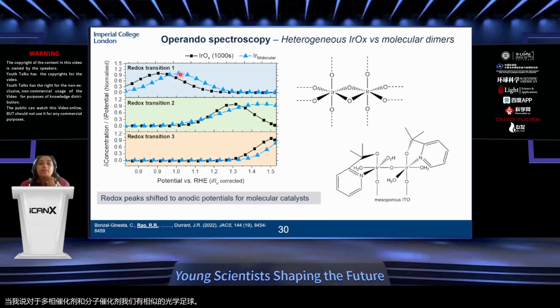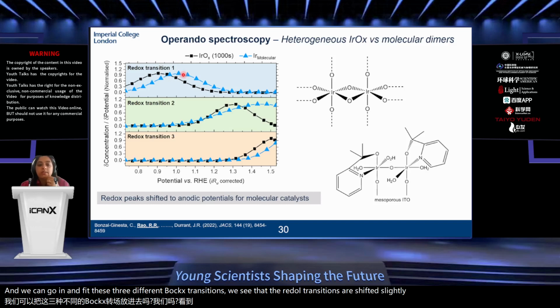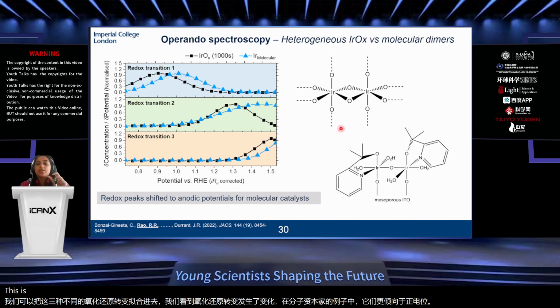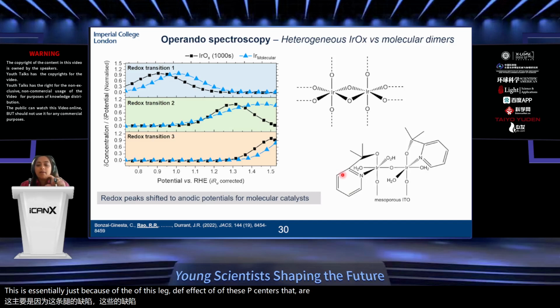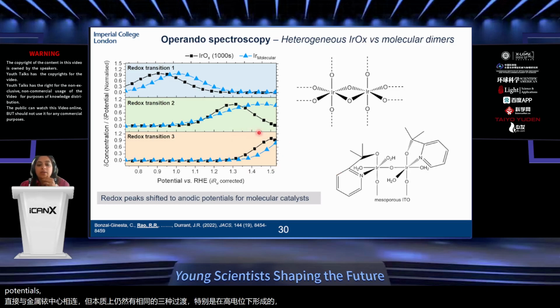we can fit these three different redox transitions. We see that the redox transitions are shifted slightly to more positive potentials in the case of the molecular catalyst, and this is essentially just because of the ligand effect of these pyridine centers that are directly bonded to the metal iridium center. But essentially, you still have these same three redox transitions, particularly the one that forms at high potentials that we've been measuring the kinetics for.